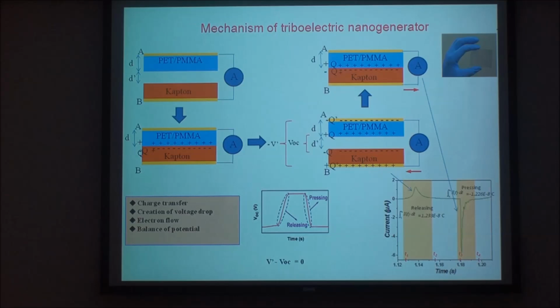Any reason why it's asymmetric? You mean this? The peak is much higher, because when you press it and you release, the rate is different. If you had a symmetric compress and release, you should see a symmetric peak. The reason you don't see that here is that release could be a little faster, so the peak is higher. But the total charge remains the same. So this is the why.